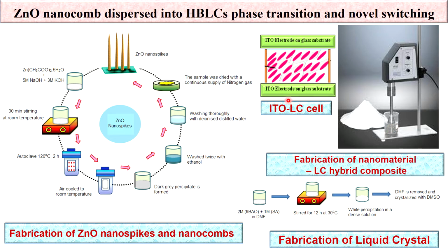And this shows the setup of the ITO liquid crystal cell, that is, the indium tin oxide liquid crystal cell. Here the ITO electrodes on a glass substrate are separated by a spacer of around 2 micrometer. And the nanomaterial dispersed liquid crystal is uniformly distributed into the space between the electrodes through capillary action.